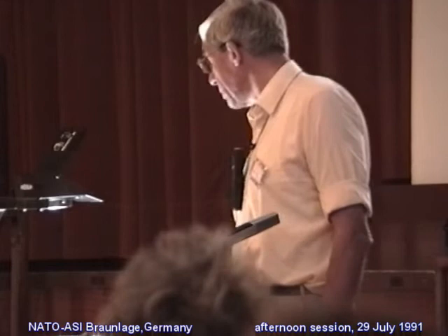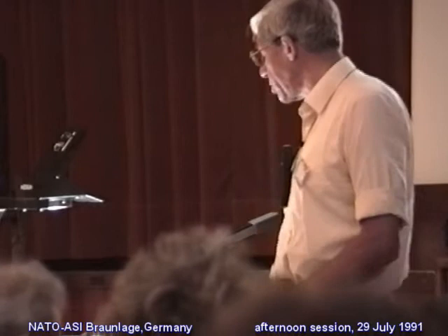The pressure on each body must be equal and opposite. So we have the mutual contact pressure, and the displacements are in the ratio of the plane strain moduli, 1 minus Poisson's ratio squared divided by Young's modulus. And that is the relationship which determines the distribution of pressure on this area. It's an integral equation for the pressure distribution.